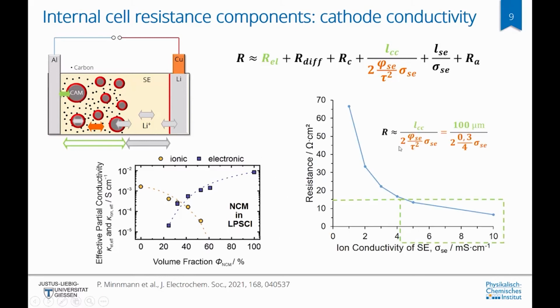We can also estimate the ohm square centimeter contribution roughly using this formula, which divides the composite cathode layer thickness by the volume fraction of solid electrolyte, its tortuosity of ion conduction, and the conductivity of the solid electrolyte. Plotting this, we can obtain the resistance versus the solid electrolyte conductivity, which is plotted here in this diagram. And if we say 15 ohm square centimeters should be allocated to the ion conduction in the cathode composite, we see that at least 4 to 5 millisiemens per centimeter is required for the ion conduction in the composite cathode.